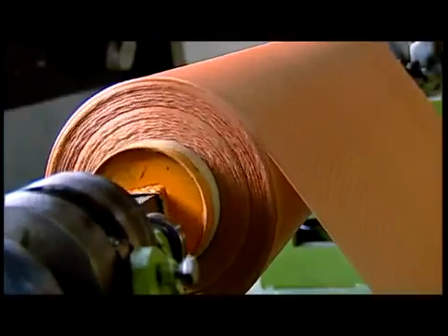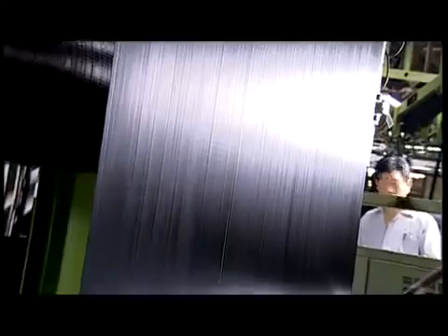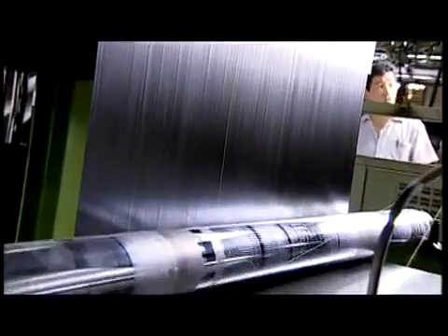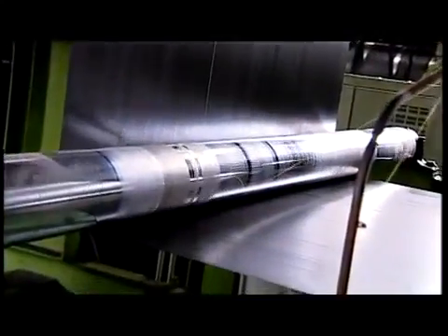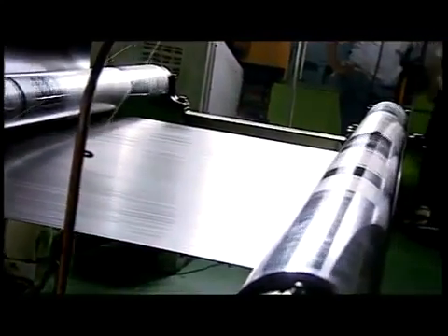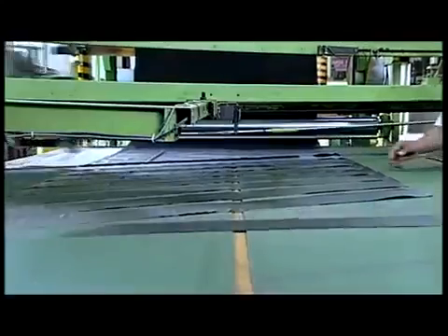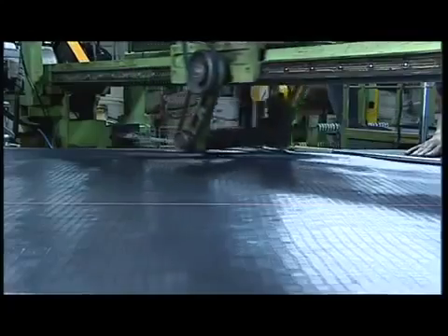The carcass, essentially the tire's backbone, begins here. A dense nylon fabric is rubber-coated, absolutely evenly and as thinly as possible on both sides, in order to achieve an optimal tire weight and, in addition, to ensure that the tire is perfectly balanced. The coated fabric is cut at a 45-degree angle and then rejoined. Only by applying this angle in the rotational direction can the carcass give the future tire the necessary stability.